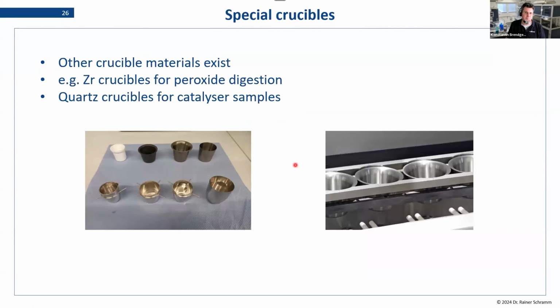Last remark here: we've been talking about platinum a lot now. There are different materials that we can use for crucibles in fusion. For example, there is the metal zirconium, this one in the picture, which is used for peroxide fusions. And there is also quartz, this one, which is perfectly fine for catalyzers where we're actually looking for platinum. So using a platinum vessel is a bad idea. There are alternatives if platinum is not feasible.